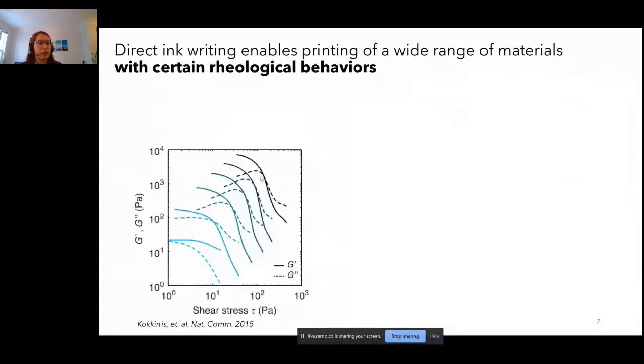Now, the limitation with direct ink writing is that you can only print inks that have a certain range of rheological behavior. So they have to flow in a certain way. What we're looking at here is a plot of a variety of different materials where we've plotted the storage modulus and the loss modulus as a function of the shear stress imposed on that ink.